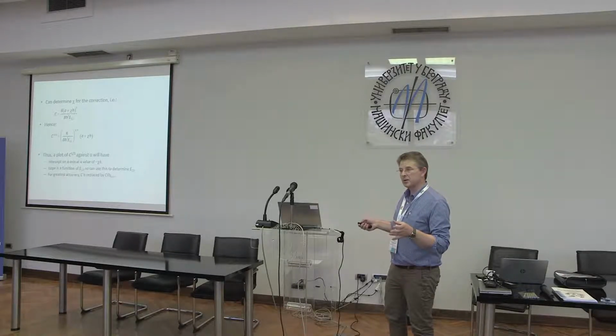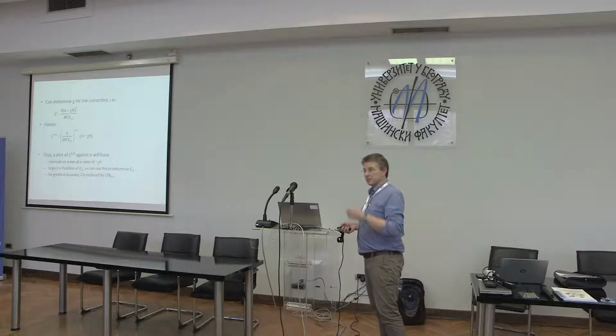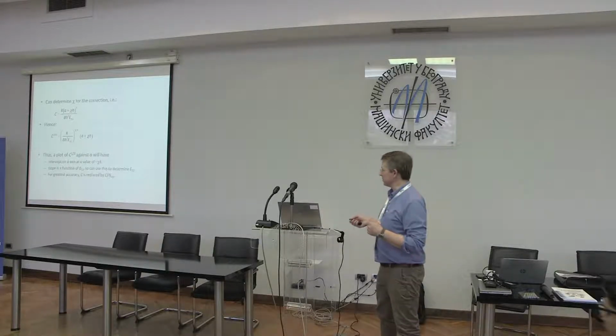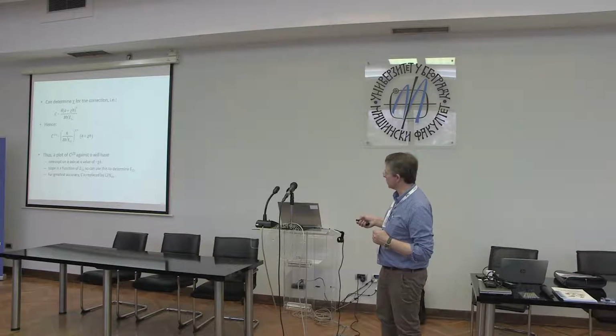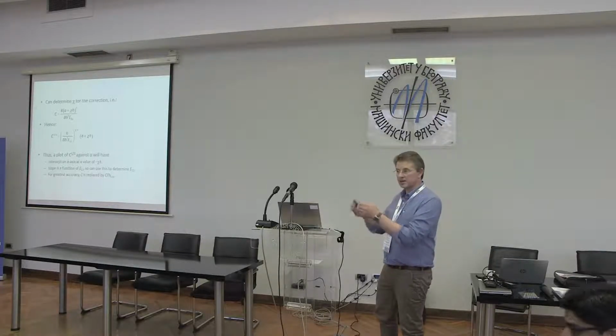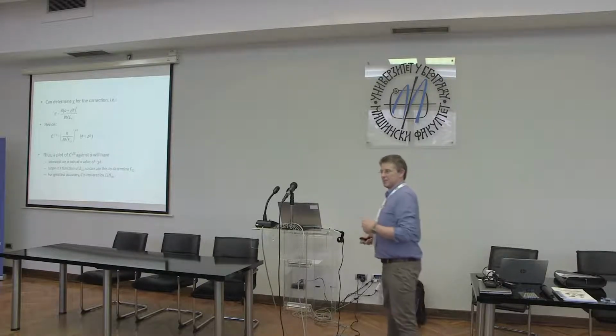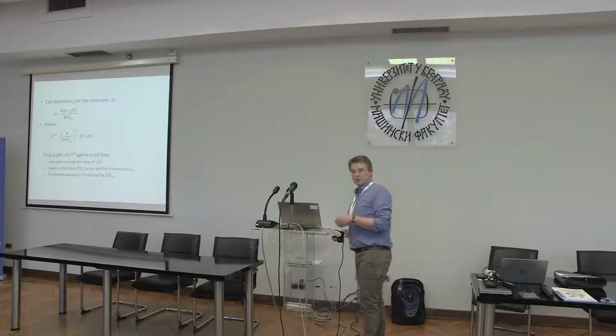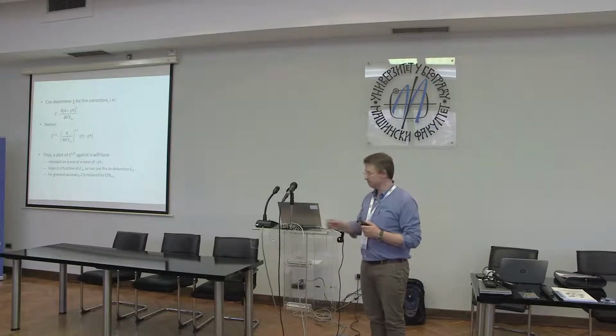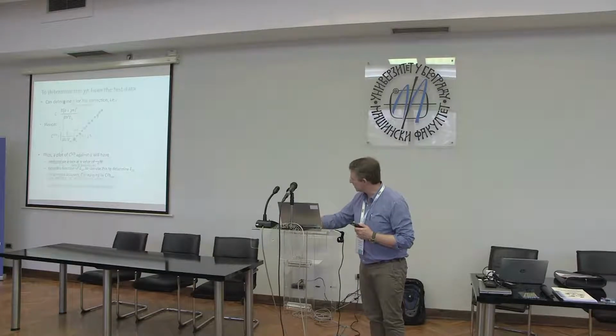plus this correction term, which is a parameter chi multiplied by the thickness of the specimen arm h. So this correction term is a length correction term, and it's that physical distance ahead of the crack tip that we have to move to get to our built-in condition. So it works quite nicely.